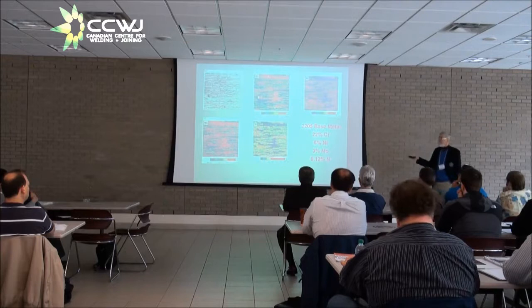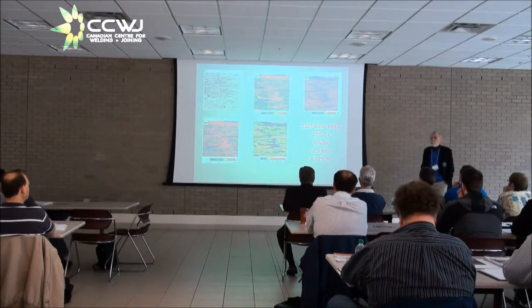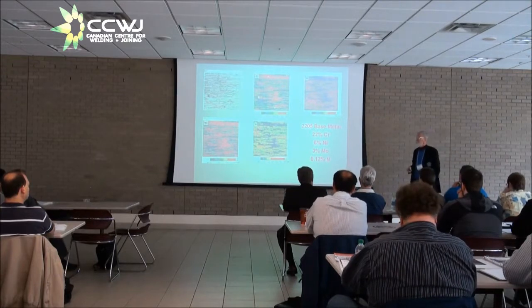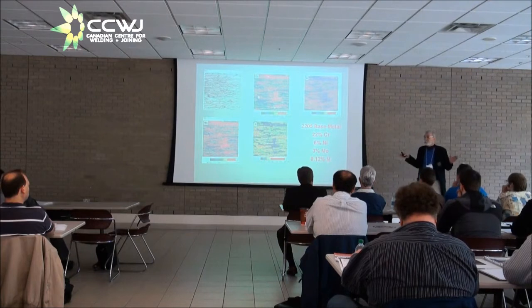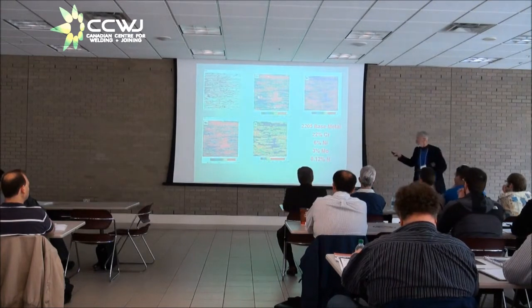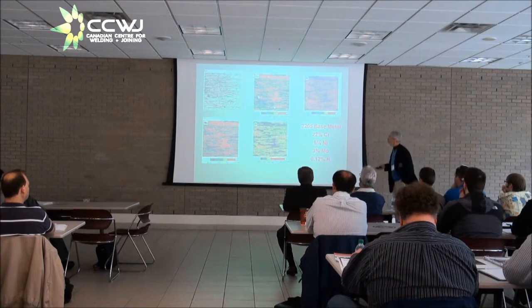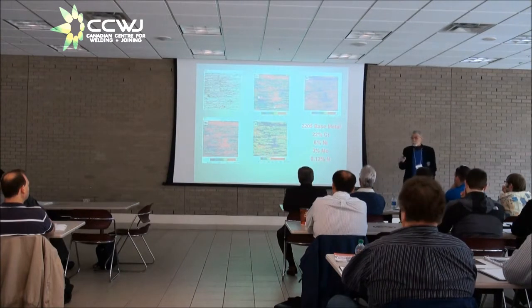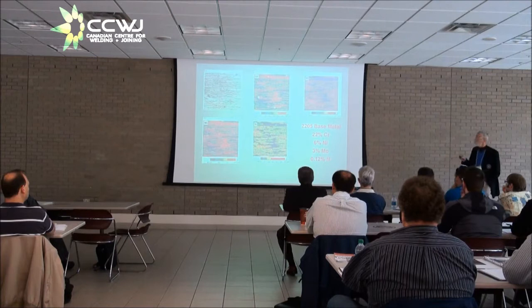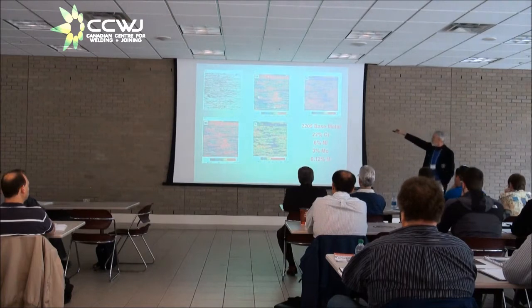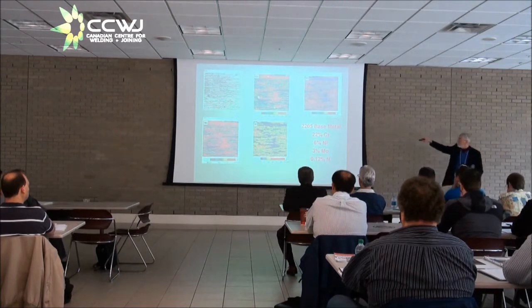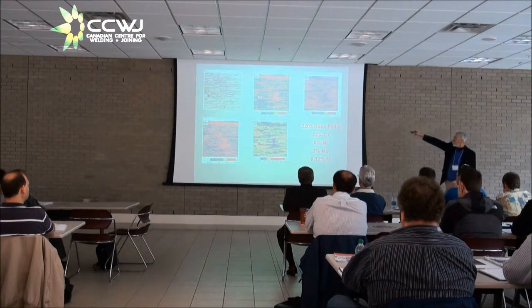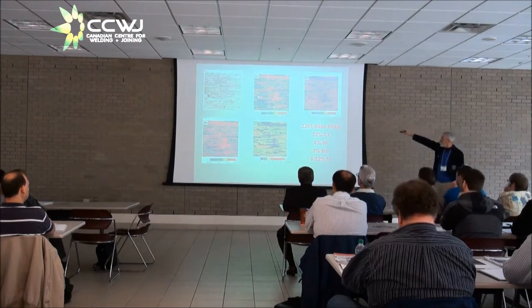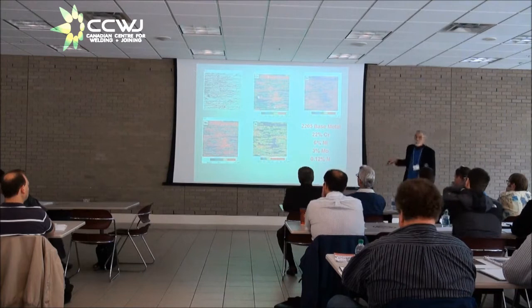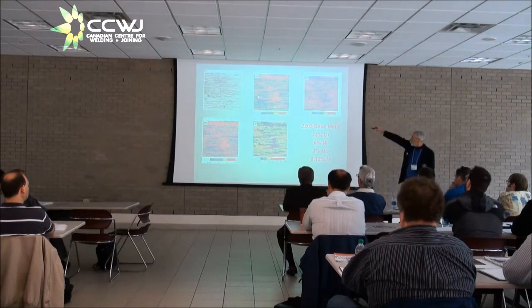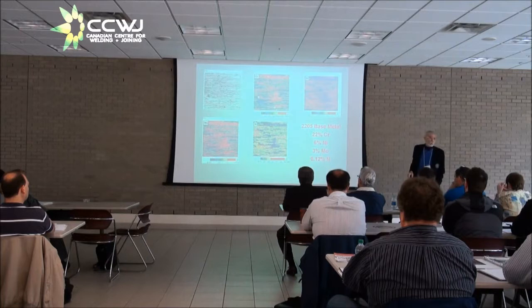But they had a second publication of it that appeared in the IIW Commission 9. And I saw that. And it was one of those aha moments. I get it. So let me go through this in a little detail to point out what they discovered and how important it is for us. Okay. So what you have here is a wrought 2205 type base material. In the upper left corner, you see the base material in the wrought form, and you can see the layered appearance. The grayer material is ferrite, the white material is austenite.